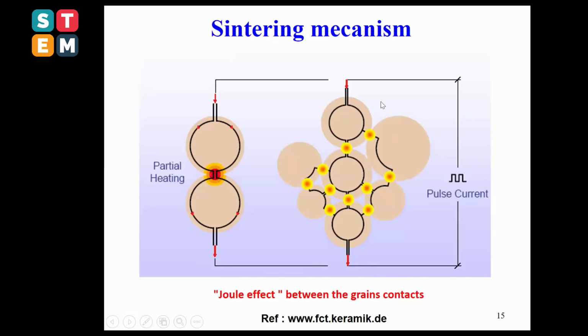Basically, let's just say when you put the powder inside the mold and during the heating, according to the FCT, you can clearly observe here, you start to heat, let's just say between the grain boundaries here by Joule effects, before heating all our powder sample.